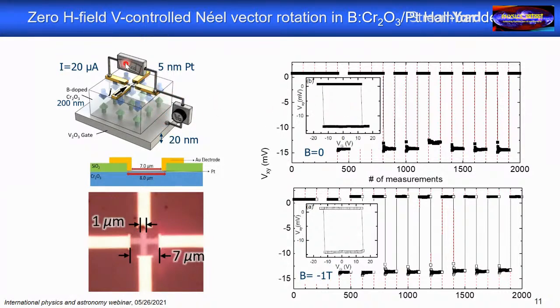And then we see in this transverse Hall voltage, we can switch between two stable states, one that has almost zero transverse voltage, and one that has a strong non-zero voltage. And we switch between the two in a hysteretic way. Now, here you see pretty much a similar result, a switching between these two different states on applying voltages of different polarization. To play it safe, we applied here minus 25 volts. You see that's an overkill. We could already switch with about 10 volts or so, but we wanted to make sure that we really switch.